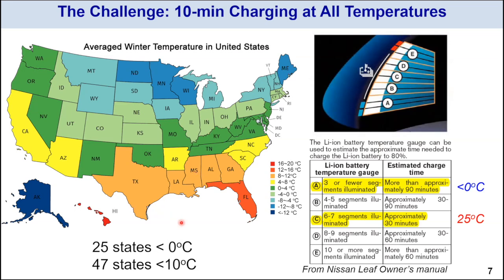And you see basically 25 states below zero and 47 states below 10 degrees Celsius. Whereas the fast charging capability is very sensitive to ambient temperatures. So I take a snapshot of a Nissan Leaf user manual here. And as you can see, a normal fast charge at room temperature takes 30 minutes. It will take 90 minutes if it's sub-zero temperature.